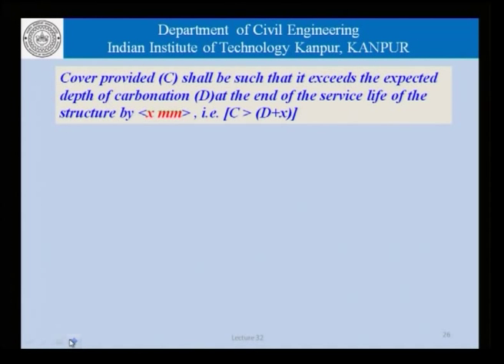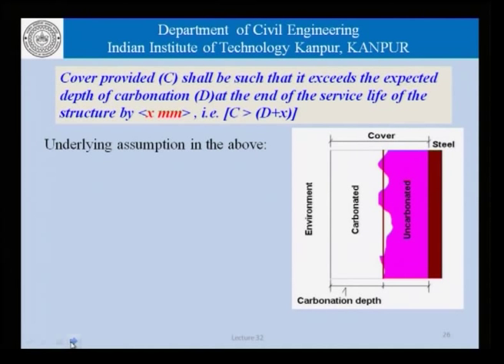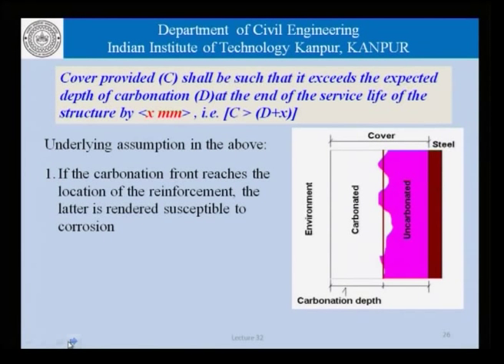Now, let us examine this provision that we wrote: provide a cover depth C such that it exceeds the expected depth of carbonation D at the end of service life of the structure by x millimeters, a little more. The underlying assumption in this statement is one, if the carbonation front reaches the location of the reinforcement, the latter is rendered susceptible to corrosion. That is, if this x becomes 0, that is the entire concrete up to the reinforcement location is carbonated, then this steel is rendered vulnerable to corrosion. Now, this is the first thing that we have assumed when we are making a statement of this nature.